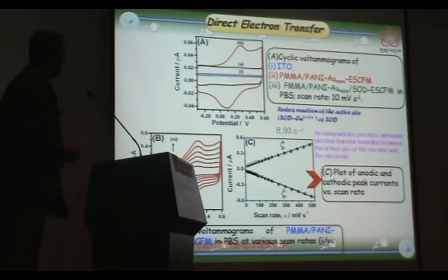So this is the electrospun fiber in the absence of the added components, and this is the electrospun fiber in the presence of the added components. You can see the surface roughness, and that corresponds to the inclusion of the polymer layer as well as the gold particles. Okay. So we could find direct electron transfer.